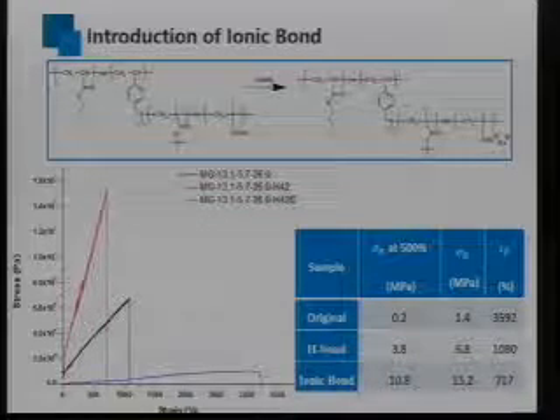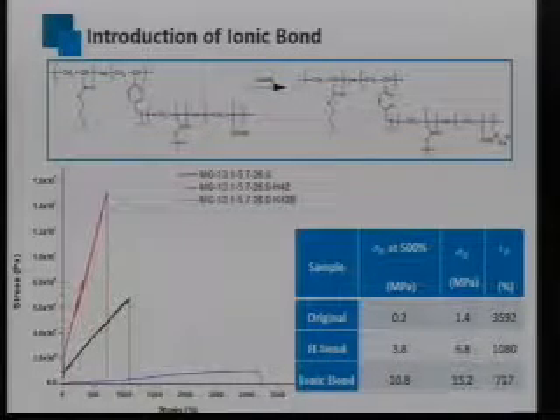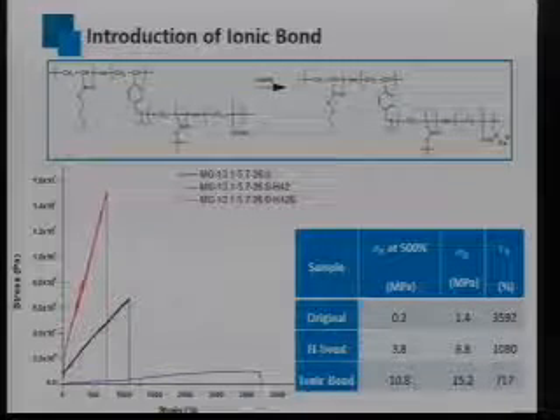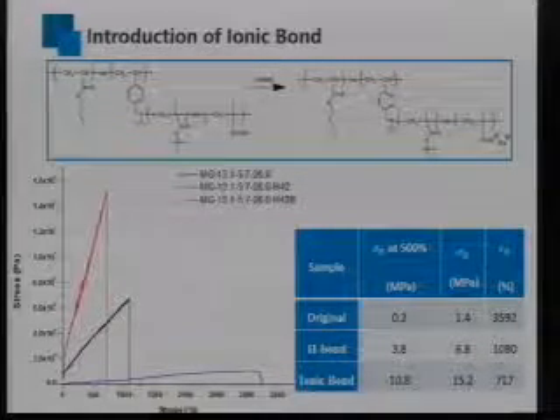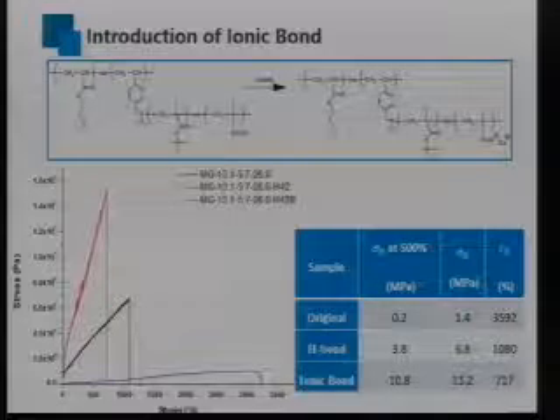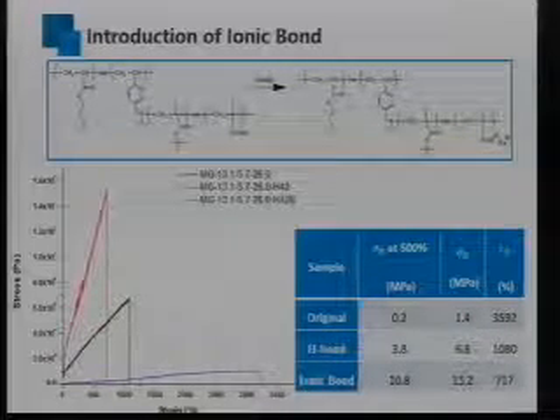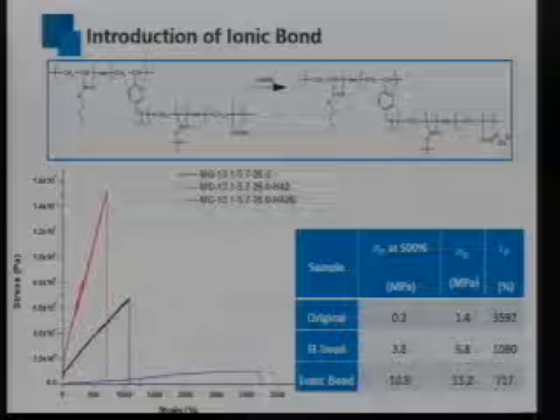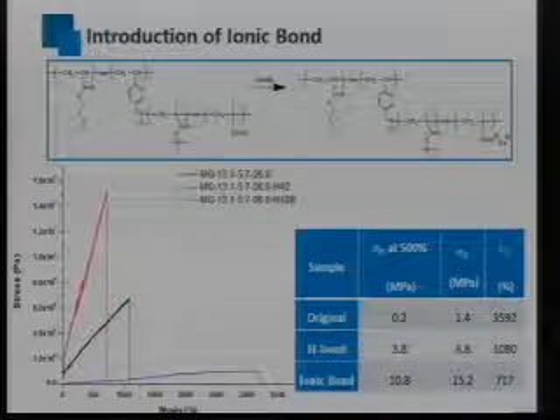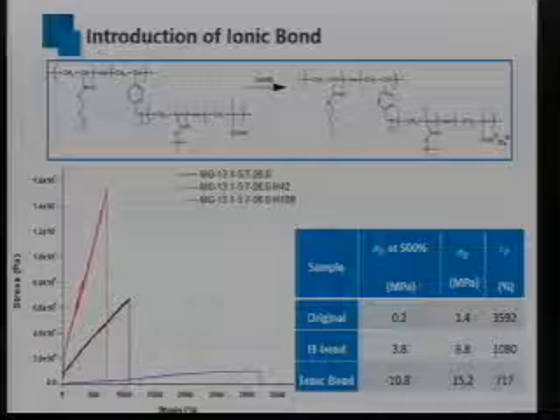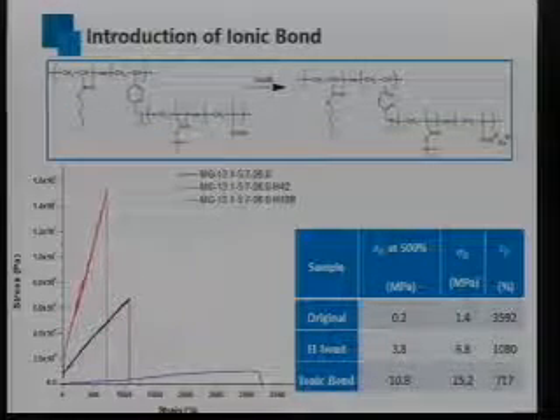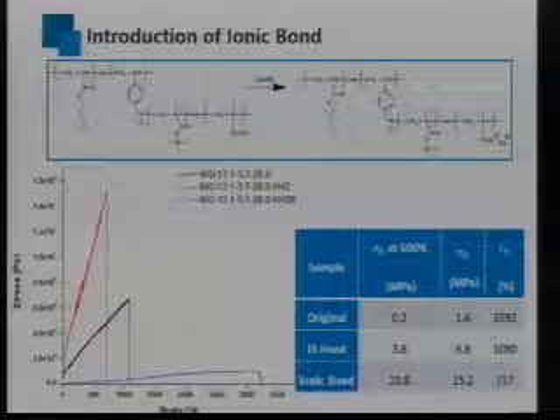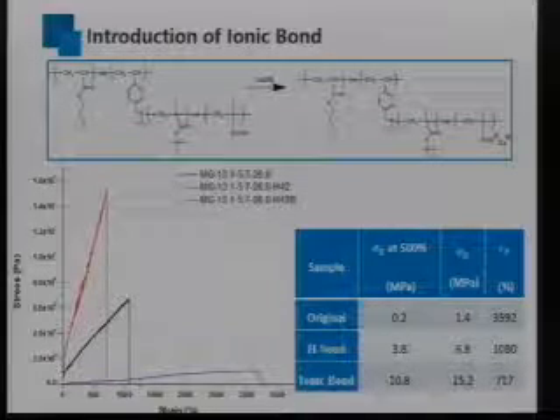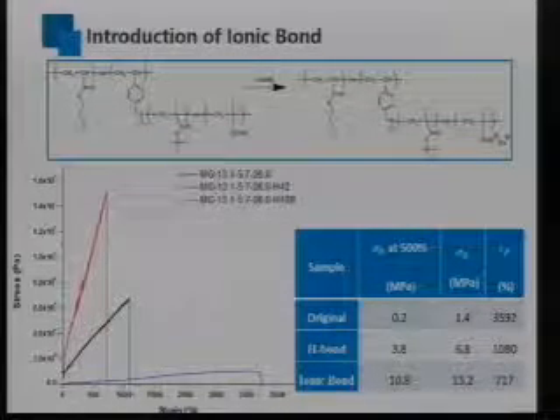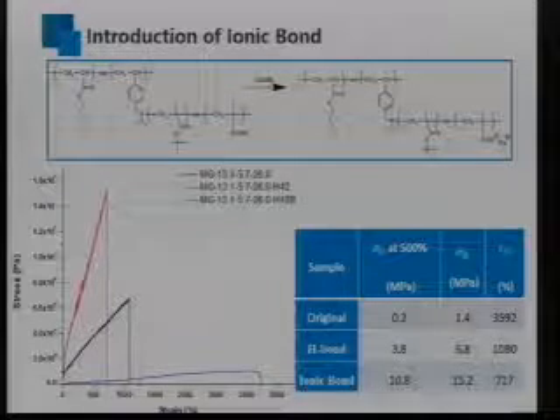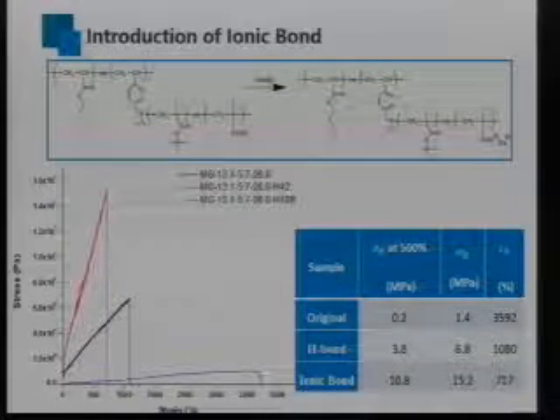after the introduction of ionic bonds, it showed a mechanical strength as high as 15.2 megapascal, with the elongation higher than 700%. When we compare the mechanical strength at 500% with the introduction of H bond, it showed an increase of around 19 times for the mechanical strength, and a further around 3 times higher increase of the mechanical strength by the introduction of ionic bonds.